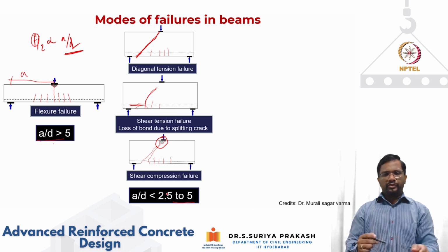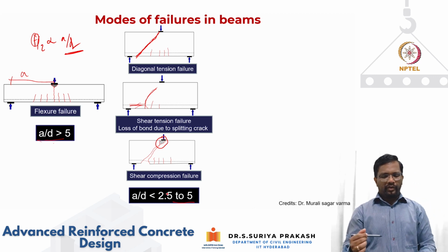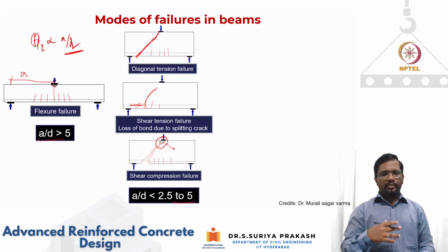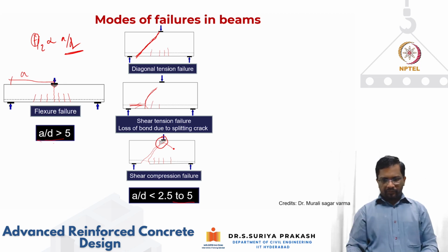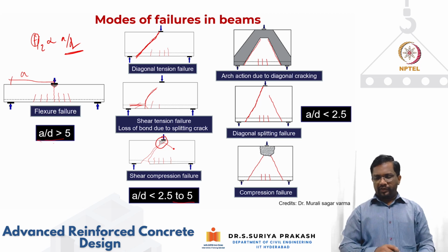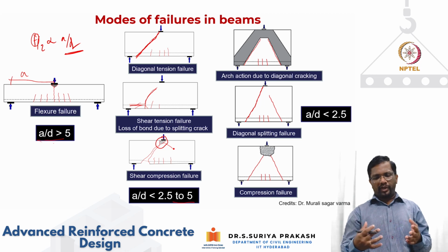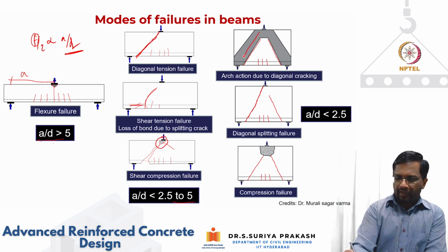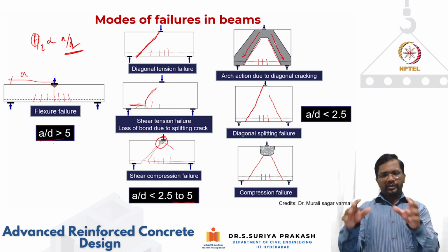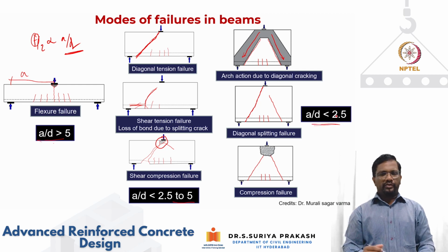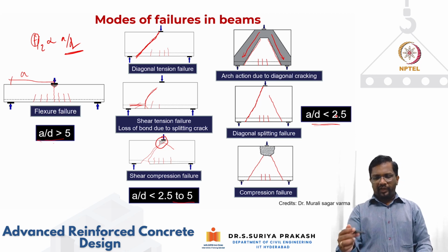So when you test a beam at an A by D ratio between 2.5 and 5, all three modes of failure are possible. At this location, for example, your principal compressive stress can exceed the compressive strength of concrete, and you can get this kind of failure. Now, when you have a shear span to depth ratio less than 2.5, as we have said, the action will change. It is not going to be dominated by bending action. It will be more like an arch action, so the loads get directly transferred to the support like this through formation of struts and ties. When you test a beam at a low A/D ratio of 2.5, you can have this kind of strut formation.